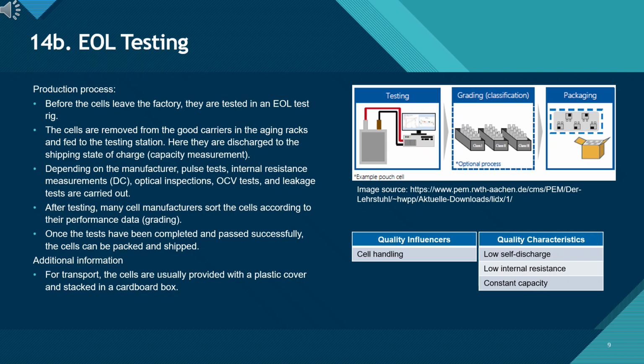Depending on the manufacturer, several additional checks are performed: DC internal resistance measurement, pulse power testing, OCV verification, leakage inspection, and optical surface checks. These tests confirm that the cell exhibits low self-discharge, stable capacity, and proper internal resistance, key quality characteristics shown in the table.